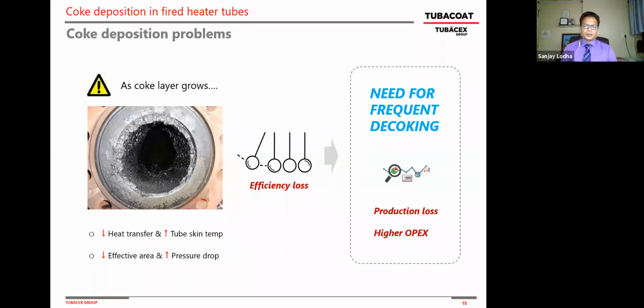So as you can see looking through the tube, as the coke layer grows, your heat transfer reduces, you have tube skin temperature that goes up, you have hot spots, your effective heat transfer area is reduced, you have a pressure drop, and you come to the point of end of run, either due to high temperatures or due to a pressure drop. And what you have to do is shut down, or do online spalling, or you have to do steam air decoking, or you have to do mechanical pigging.